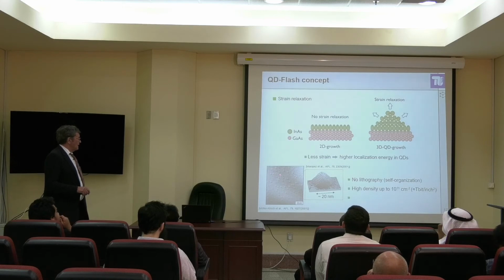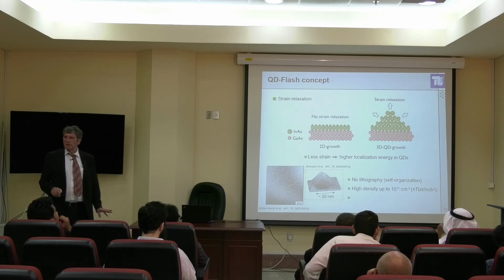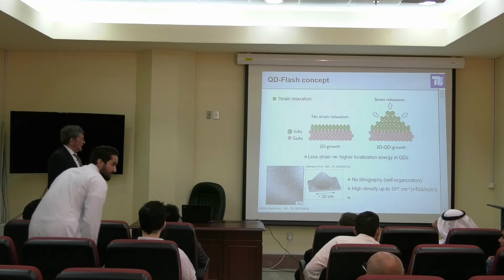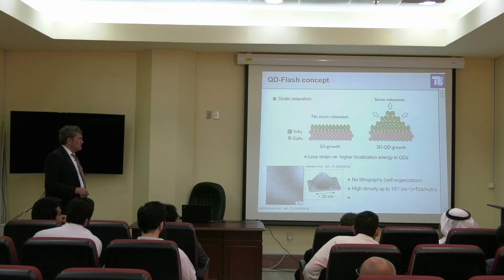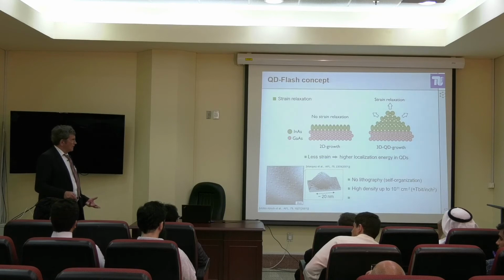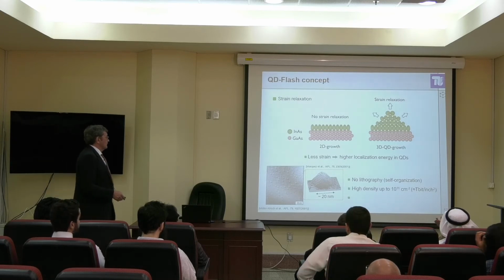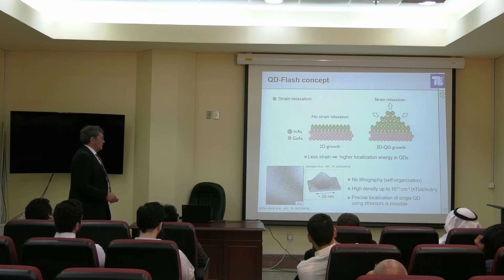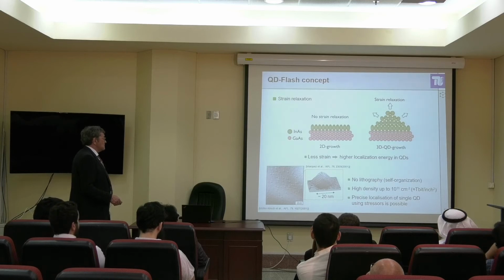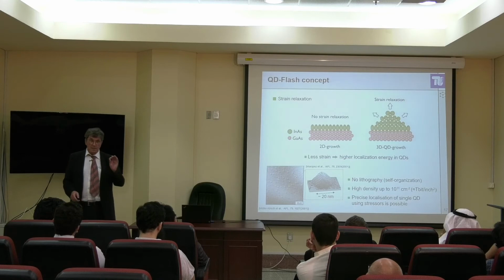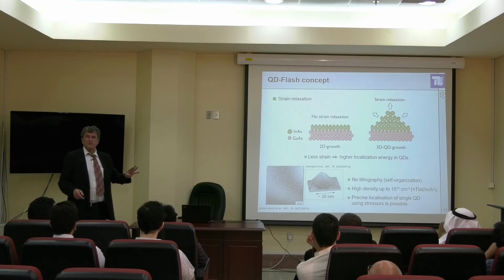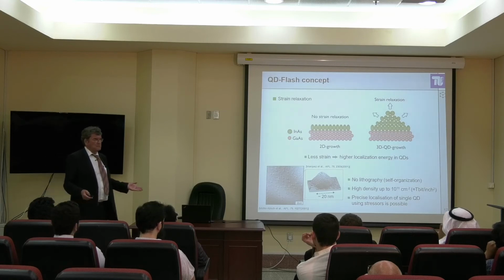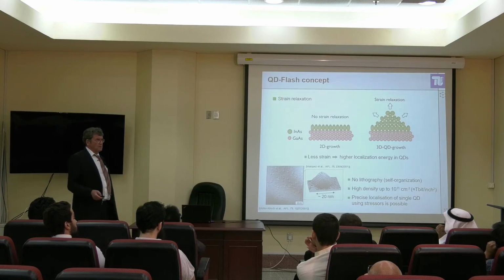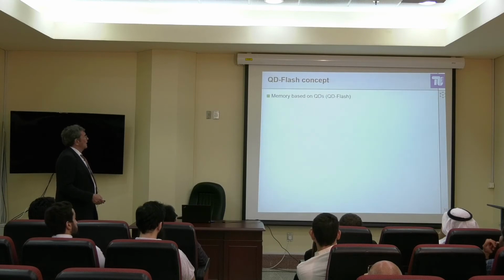And for forming such quantum dots, you don't need lithography, it's self-organization. And you can create a very high density of such dots, terabit. That means a memory can have a terabit per square inch, which is a record, if you would fully exploit it. And finally, what we have developed is precise localization of single dots using stressors. So you can precisely localize it. Again, a material science subject, not something you would be really interested in, but probably the Nanotechnology Center, which we visited an hour ago, covers how to localize such quantum dots.